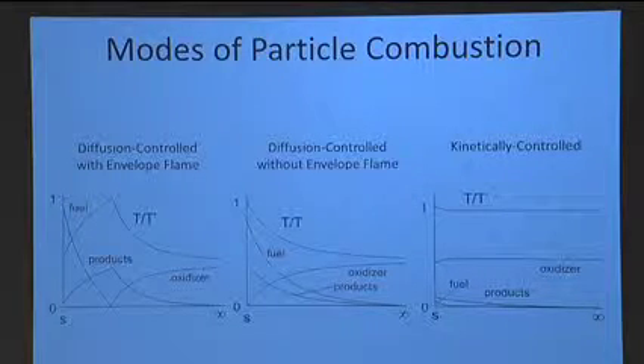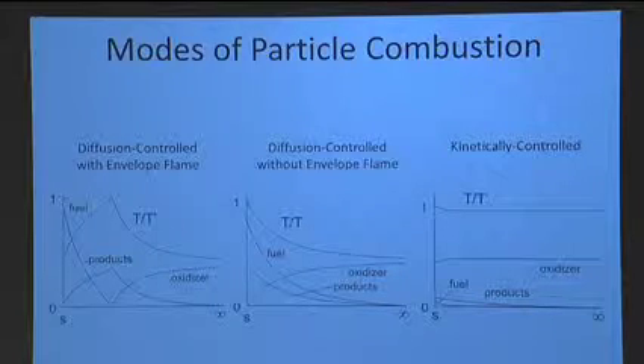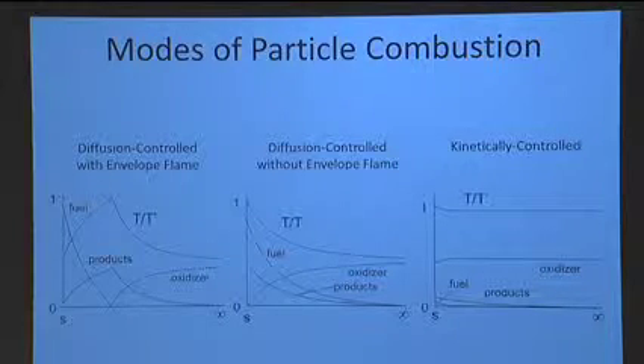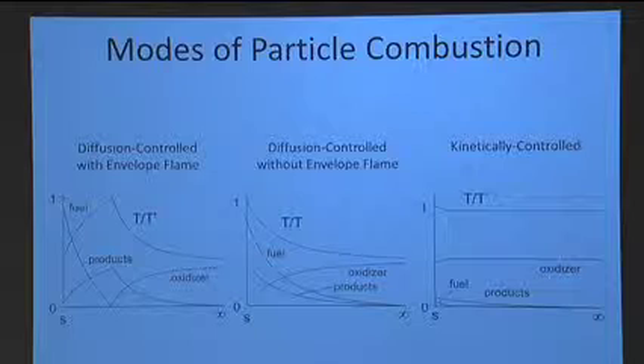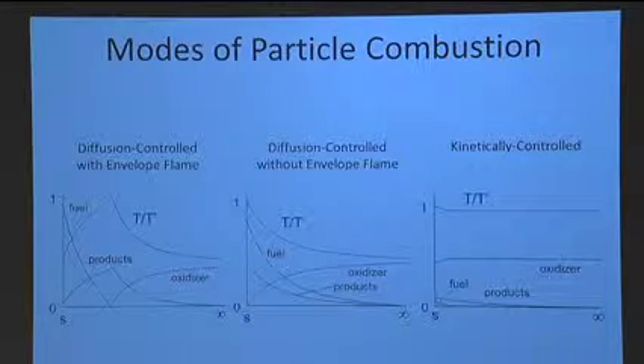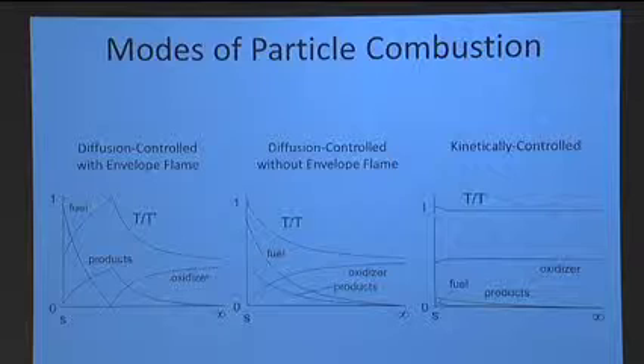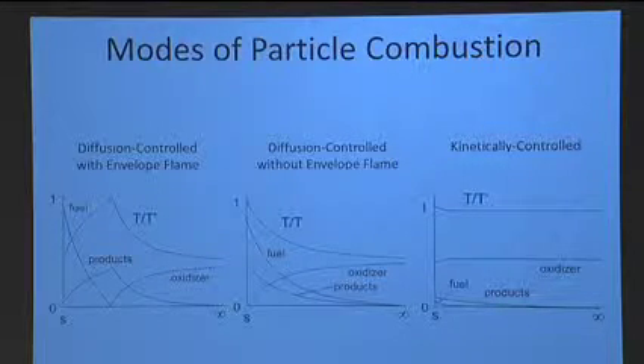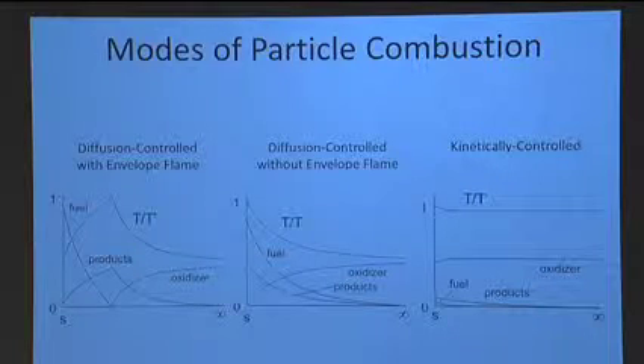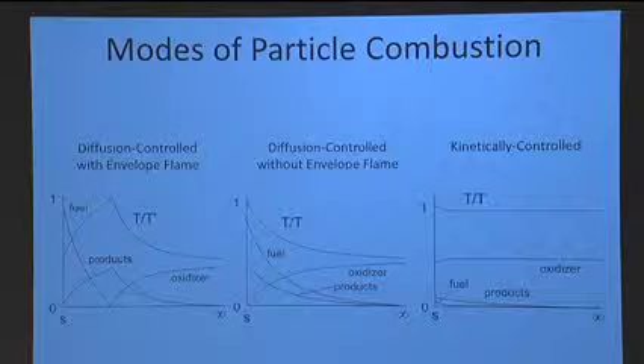And so in those sort of cases, since I have very fast transport, my mass and energy is moving freely around, I lose all spatial gradients in the surrounding environment around, say, a surface. And so what you see here is if this was a surface reacting here, I potentially would have my oxidizer diffuse very rapidly up to the surface. It would react and be transported right away as products, and I'd have very little fuel out here. And the temperature distribution across the domain would be very simple, because even if this was a very exothermic reaction on the surface, I would have very high transport rates that could start to bring the temperature down close to the environment temperature.